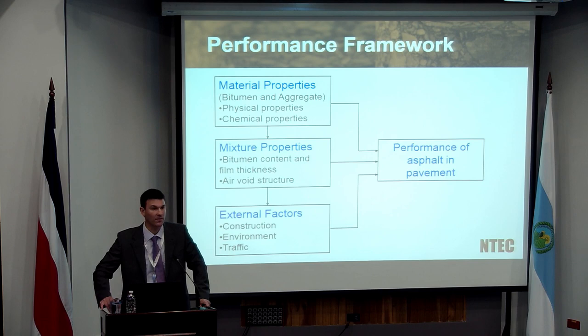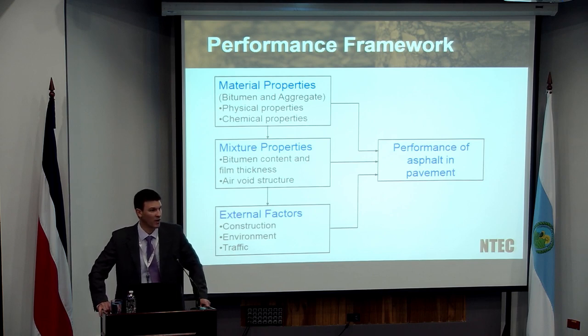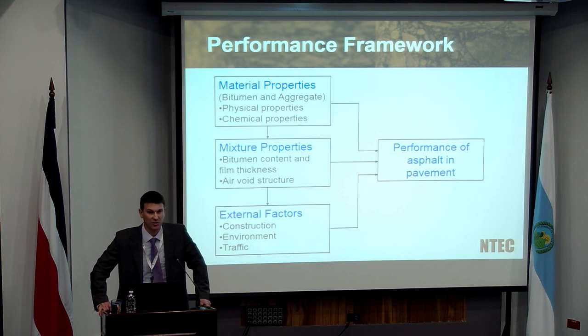And finally, external factors. And a lot of this was for a research group outside our control, but obviously construction is a big issue. We found, based on a large literature review and a survey of typical types of failure in the UK, that a lot of the times the materials were actually fine, but when it came to laying the materials, in terms of the construction, in terms of the compaction, the densities of those materials, that's where the issues arose. So construction, very important as an external factor.